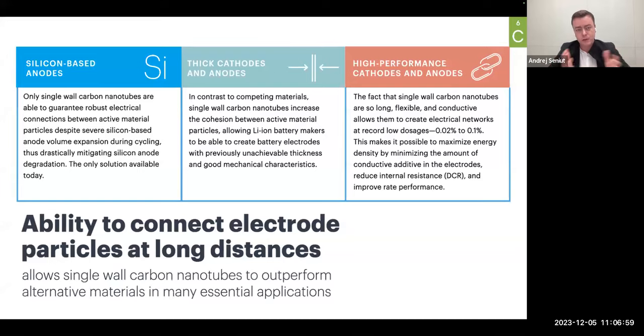The thicker you go in the thickness of your electrode, first of all, the more non-uniform is your conductivity. If you speak about application of classical conductive additives such as carbon black and multiwall carbon nanotubes, for many reasons, for example, during the drying process, because they are small, they tend to go up towards the electrode surface. And this is why throughout the thickness of the electrode, the conductivity is not uniform. And second, just imagine a thick electrode is similar to a thick layer of paint on the substrate. If the layer is too thick, it starts to crack. And here it turned out that application of single wall carbon nanotubes allows to improve both mechanical characteristics of the electrodes